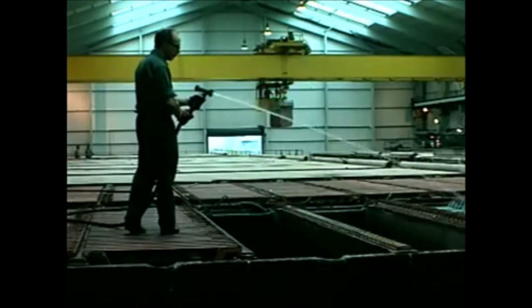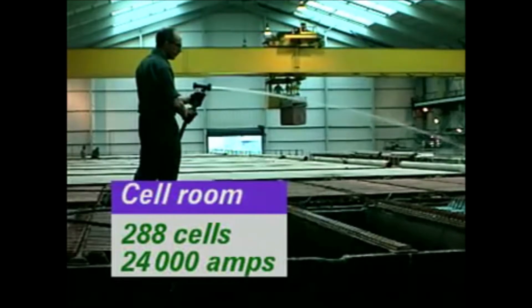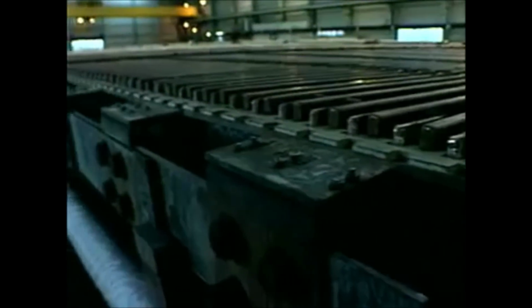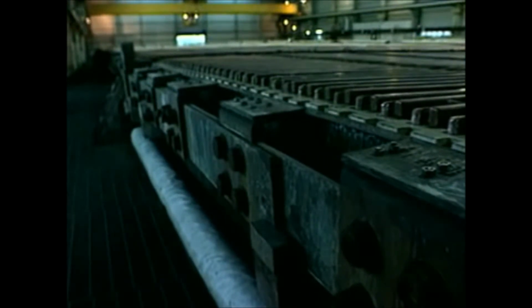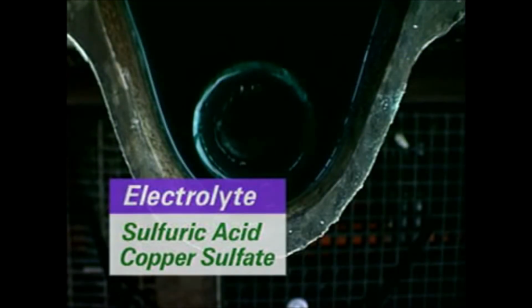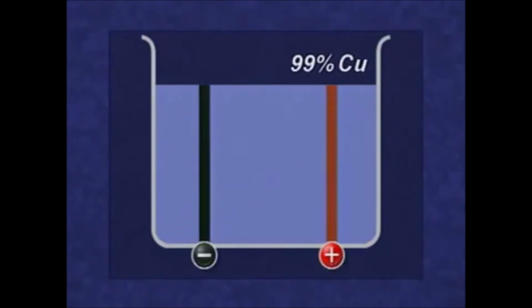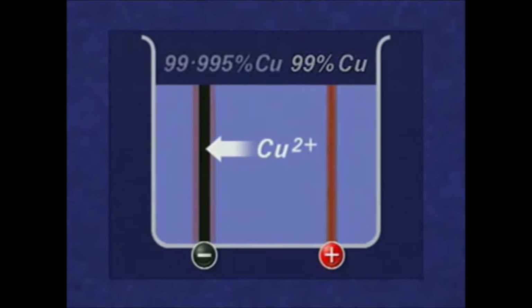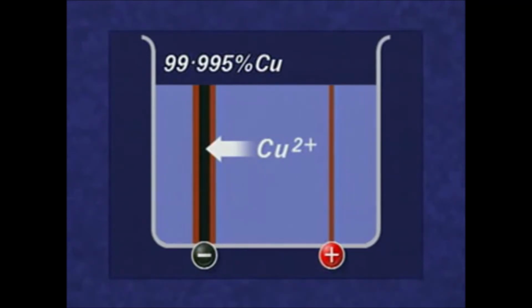This is the electrolysis cell room. It houses 288 cells and uses a total current of 24,000 amps. The copper anodes are sandwiched between stainless steel cathodes in sets of 39 anodes and 38 cathodes. They're placed in an electrolysis cell containing an electrolyte of hot sulfuric acid and copper sulfate. The anodes dissolve in the electrolyte to give a solution of copper ions, and pure copper is deposited on the cathodes. Impurities of other metals in the anodes do not dissolve and sink to the bottom of the electrolysis cell, producing anode slime. Anode slime is valuable and is sold so that the precious metal residues, including silver and gold, can be extracted.